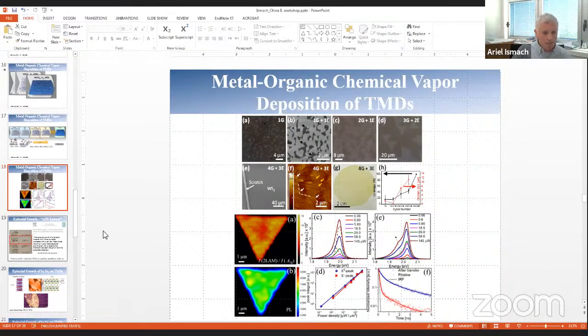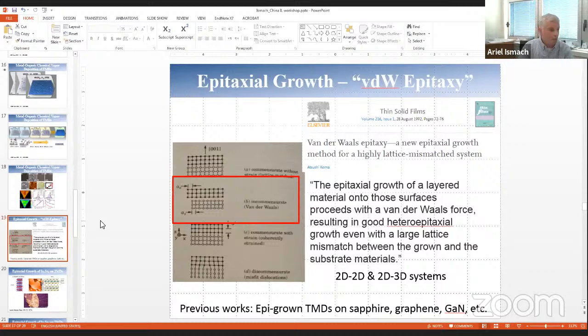Now, I would like to move to the final idea, which I think is the optimal case in order to improve the quality of the film, and it is, of course, the epitaxial growth of these TMDs. You need to understand that classical epitaxial growth means that there is a clear commensurism between the growth substrate and the film. This commensurism implies that there should be a small mismatch between the lattice parameters of the substrate and of the film. If that mismatch is too large, epitaxial growth is not possible.